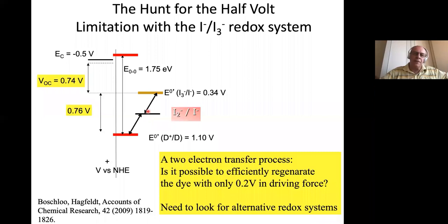The advantage with the I3 minus is that it doesn't accept electrons from the TiO2. So remember now that electrons are moving in the TiO2, and we have a high surface area, so it is close to the surface, and it may react with the electrolyte across the interface. And that's a very probable situation. And that's a loss. That's a short circuit current. The thing with the I3 minus, that's not very probable, and that's why it was used so much.